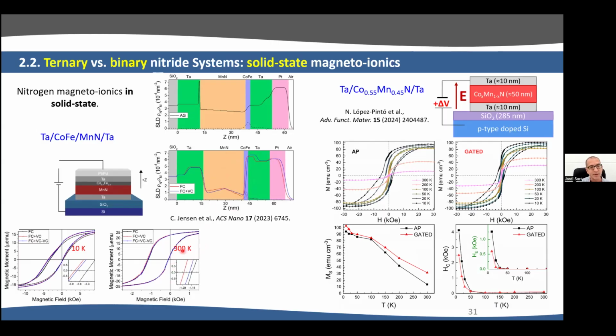and then you can modify the antiferromagnetic properties. In our group, what we studied is this cobalt manganese nitride single layer, again with the top and bottom tantalum layers. We applied voltage, and we again induced this exchange bias because cobalt manganese nitride is also an antiferromagnetic compound. Here we had some clusters of Co3N, Co4N that are ferromagnetic, and they were coupled to basically a Co2N matrix, which is antiferro, especially below 30 Kelvin. And we saw this exchange bias, and when we apply voltage, we could change the magnetization, and we could change the coercivity and the exchange bias field, all in solid state.